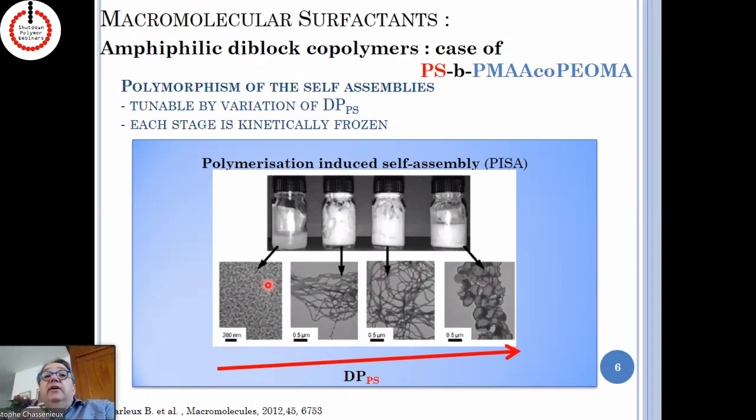But here again, all these systems are completely frozen from the dynamic point of view. There is no exchange between free polymer chains inside the solvent and the self-assemblies. It's very, very important because here, these systems behave more like fibrils than the worm-like micelles that I've shown you with molecular surfactants.